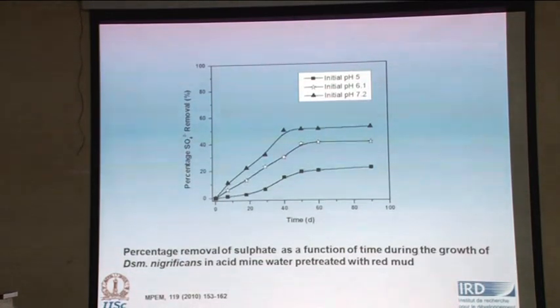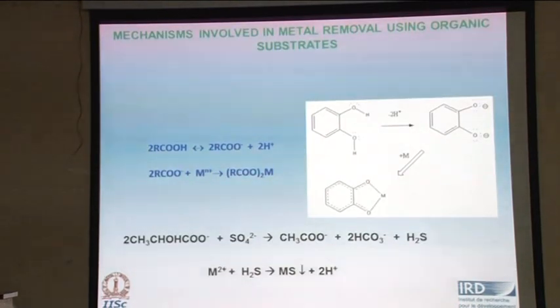But once you add this Desulfomicrobium after neutralizing the acid mine water, you will be able to get better reduction of the sulfate. So the mechanisms involved with respect to the various substrates that we have used: I talked about the carboxyl group and the phenolic groups that are present can bind with the metals. In the case of the Desulfomicrobium, the sulfate is actually reduced to hydrogen sulfide, and this hydrogen sulfide, which is biogenically produced, can be used for the precipitation of the metals as the corresponding sulfides.